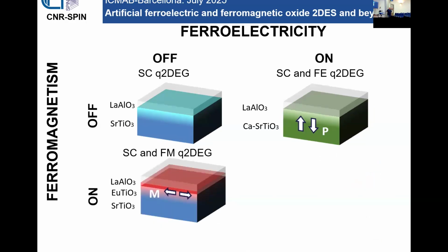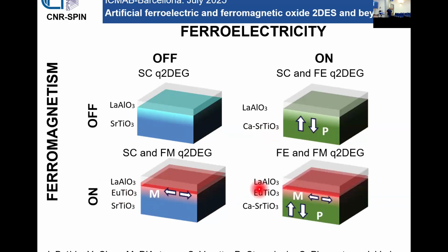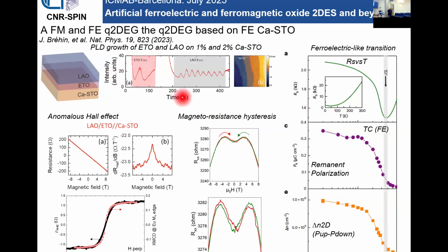Then it was natural to combine this approach and this approach to get something which contains both ferroelectricity in the bulk calcium-doped strontium titanate and magnetism in the europium titanate. This was an idea of Manuel Bibes, and it was also part of the PhD thesis of Jeremy Breen in his group. So we have realized in Naples these heterostructures, which grow quite well, together with Duchenne, actually. And this heterostructure features anomalous Hall effect, in-plane magnetoresistance hysteresis, and again a coupling between the sheet resistance and the ferroelectric transition.